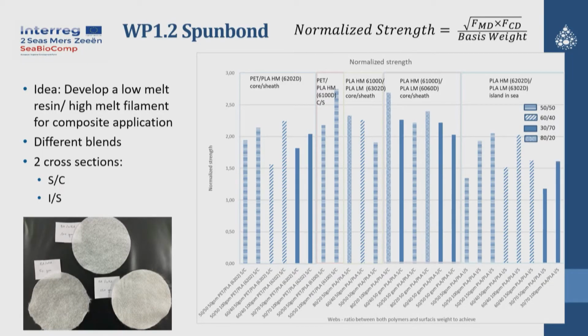So we try to complexify the study a little bit, of course, because we move to several different couples using PLA high melt, polyester, PLA low melt, and try to combine everything. So you have the results here, all the results. We also tried different cross-sections, sheath-core and island in the sea. But you can also see the tendency.